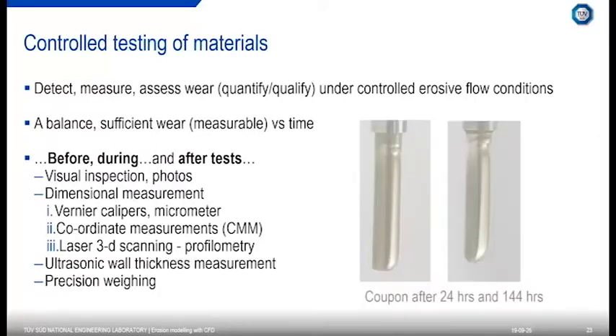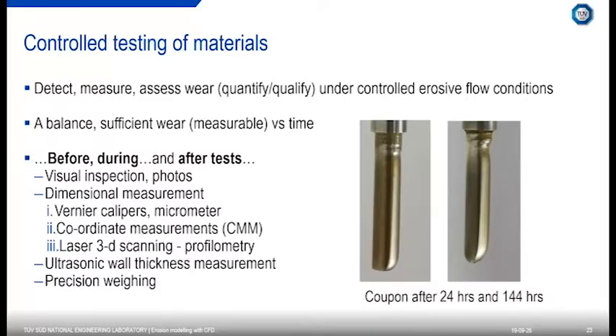And what we typically use is coupons. So here, for example, we have an example of a steel coupon, which was a cylinder, and the flow is going from right to left. And you can see how much wear has actually happened after 24 hours and then after 144 hours. And this allows us to document exactly what's happened under particular conditions.